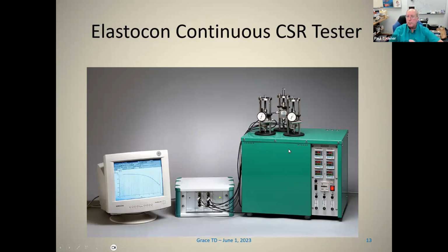They now have ones that can both heat and cool. One of the advantages of this is that you can follow multiple specimens over a temperature range up and down, and it gives you really good values. The disadvantage is that there's some configuration constraints that I get concerned about, and also it's a very expensive unit. I think the bigger unit that can do both heating and cooling with multiples is around $100,000.